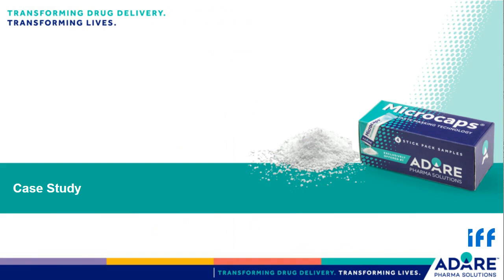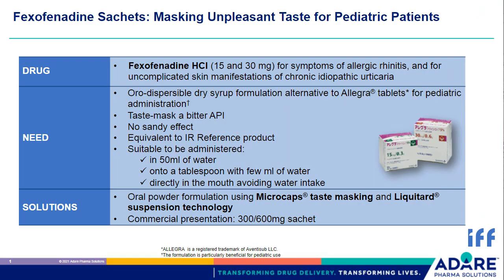And now I'm going to present one specific case study where microcaps has been successfully applied, leading to a successful commercial product. Fexofenadine is quite a bitter drug, and Sanofi was looking for a pediatric formulation for the Japanese market in the form of powder, able to mask the taste. But most important for Japanese children, particle size had to be quite small, below 200 microns, in order to minimize grittiness and particle perception.